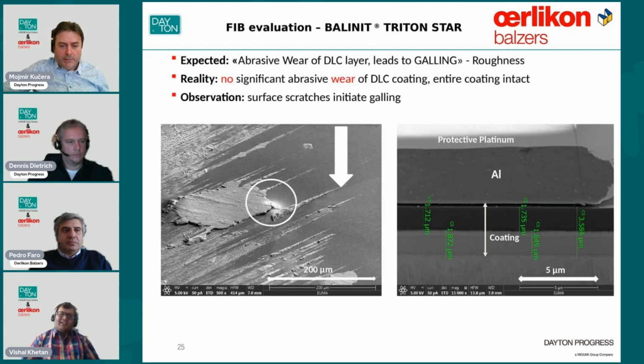Okay. And finally, we just go one step deeper here to show you how a coating really protects the tool. We have seen that the main challenge in punching is the scratches which get initiated due to different particles or residues which are released during the punching process. They start to generate scratches wherein the aluminum will build up on top. But when we visualize this sticking process, it was seen that DLC coating, first of all, can resist the whole scratching process much better than steel.